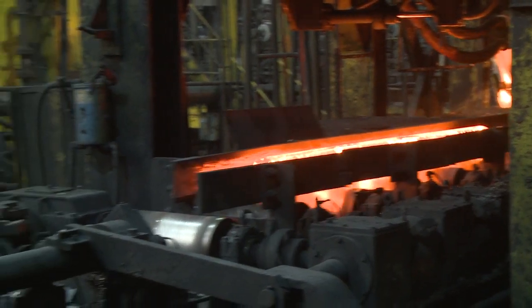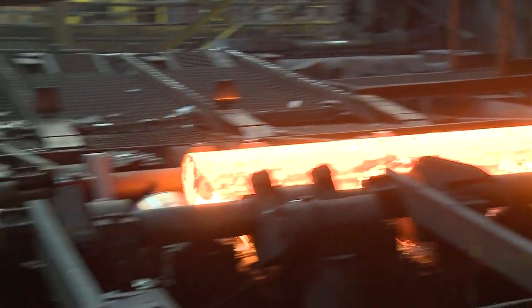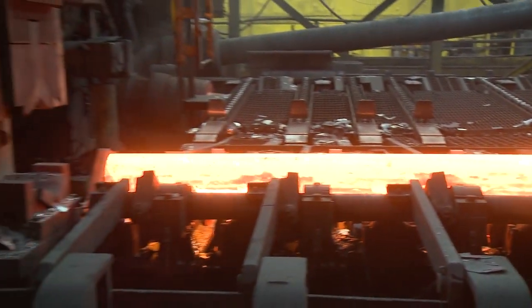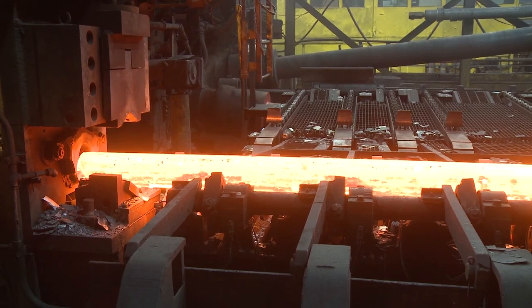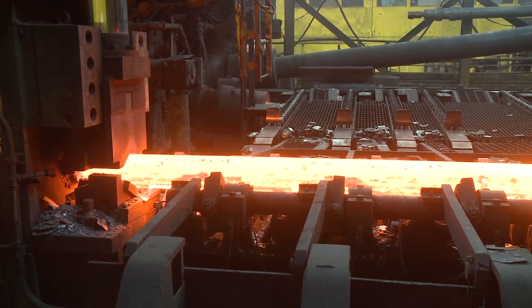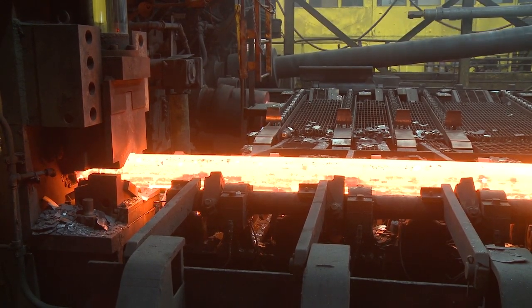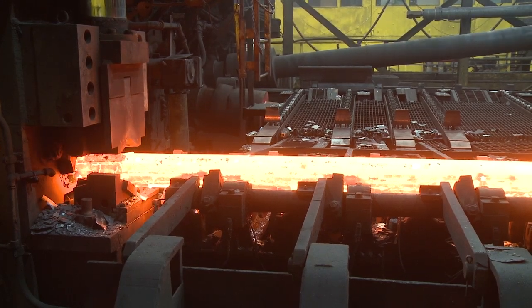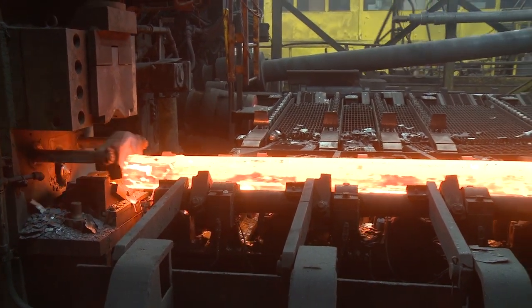We use a center punch to help ensure better wall concentricity during the piercing process. The center punch will hold the front end of the billet and then extend a punch into the billet's end to make this center indentation. This indentation also starts the piercing process.